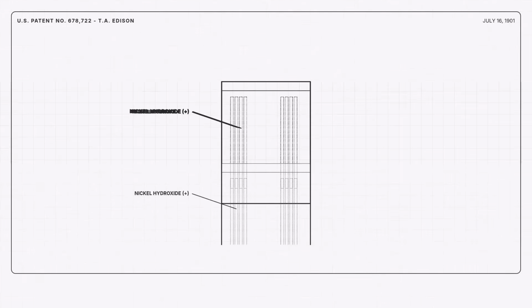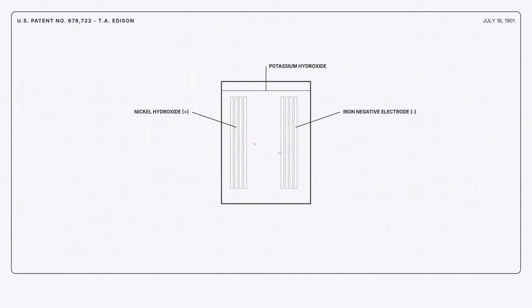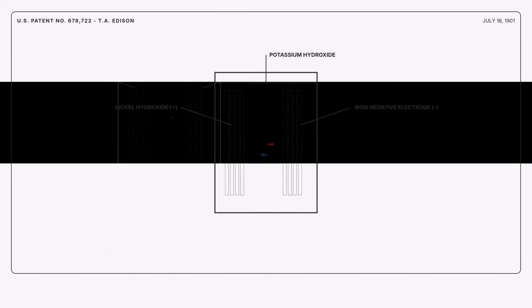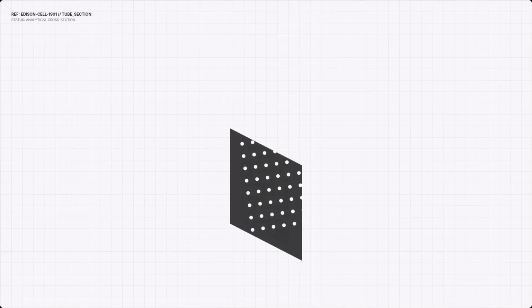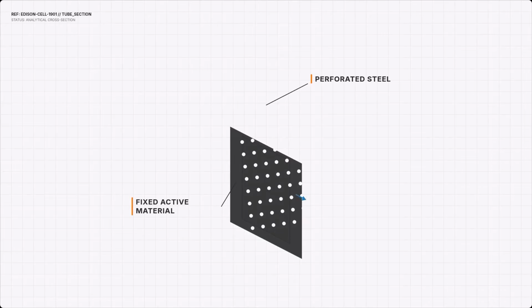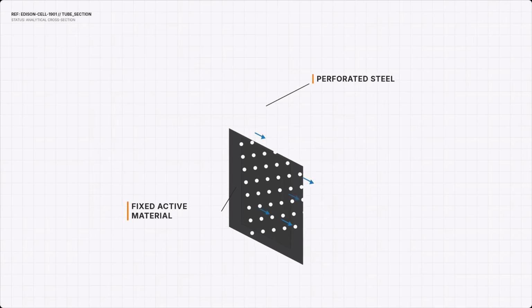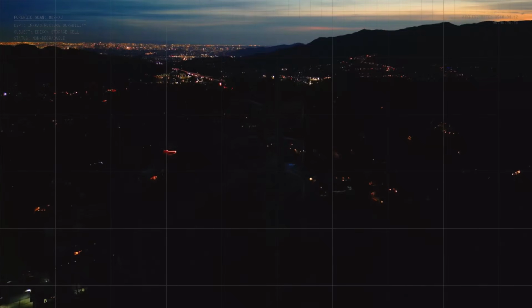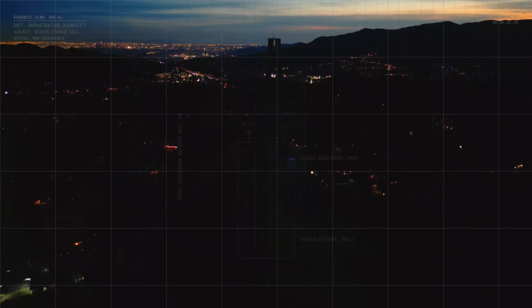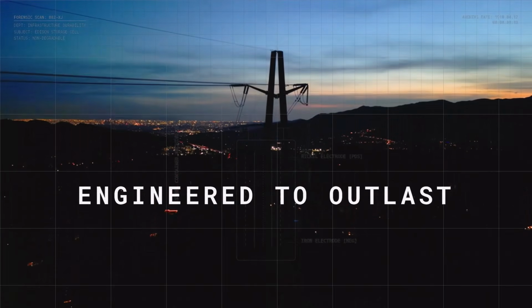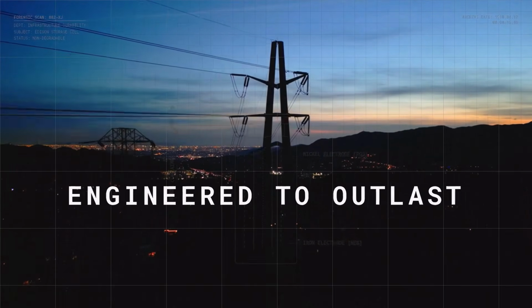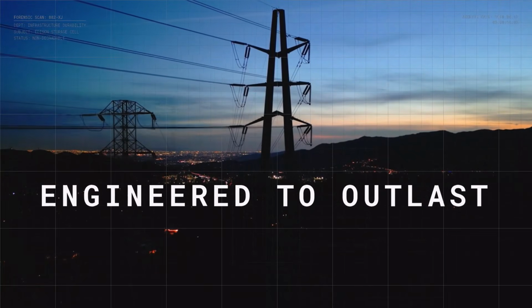His 1901 patent described a nickel hydroxide positive electrode packed into perforated steel tubes, an iron negative electrode in an identical structure, and a potassium hydroxide electrolyte solution that carried ions between them. The steel tube construction was the defining innovation. Where every lead-acid electrode degraded through the expansion and contraction of repeated cycling, Edison's steel tubes held the active material fixed. The iron electrode could not shed. The nickel electrode could not crumble. The battery could not fail through the mechanism that killed every alternative. These were not storage cells. They were the world's first battery engineered to outlast the infrastructure it powered.